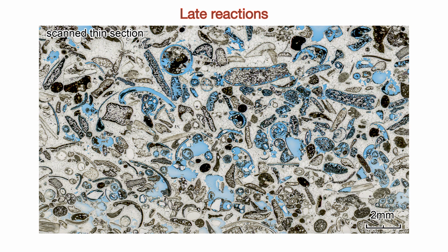Late reactions. The alteration of samples, while penetrated by fresh water for a few thousand years, is widely distributed. But after this initial alteration, diagenetic events are spread irregularly, each event creating an ever-increasingly irregularly connected pore network. Aragonite that survives the early reactions can become isolated, so even after hundreds of thousands of years, it survives in some ooids, while adjacent ooids have become oomolds.